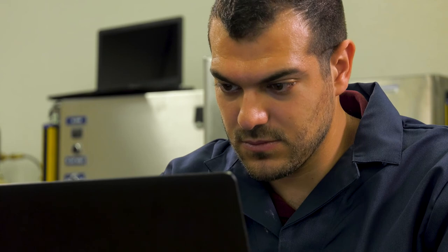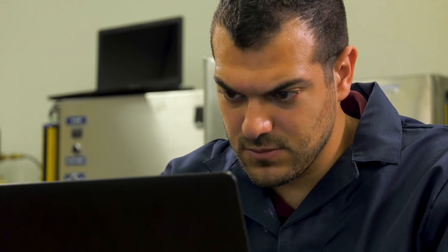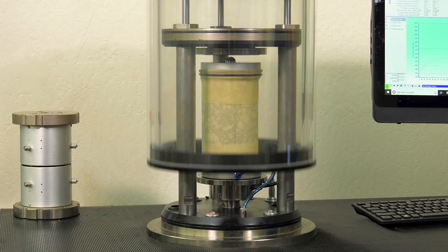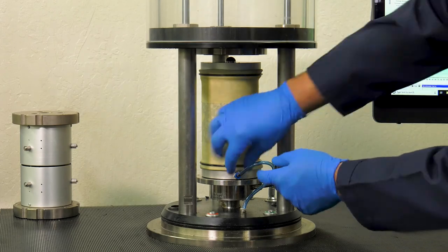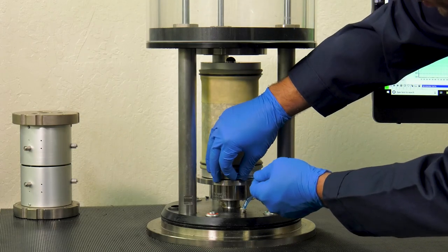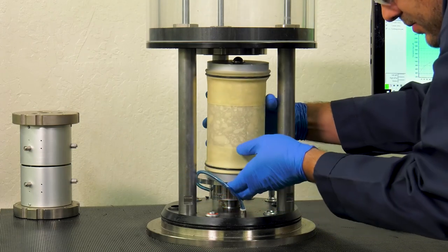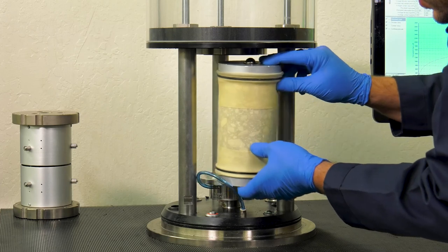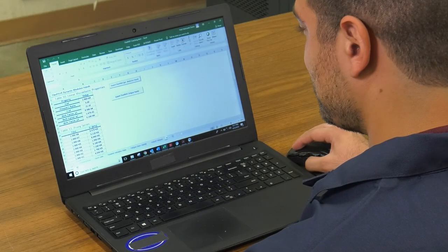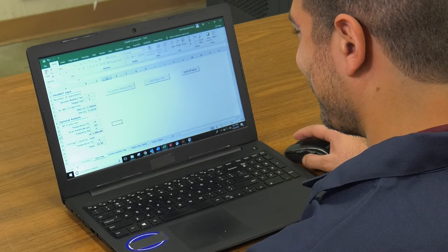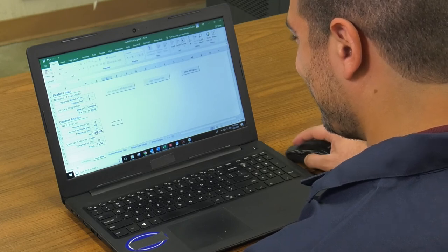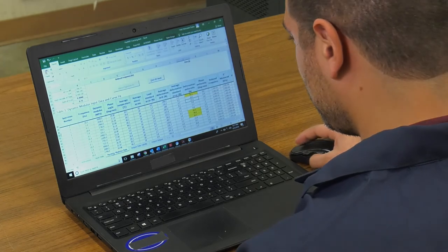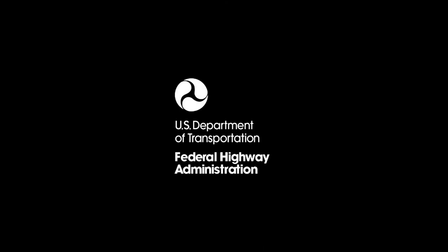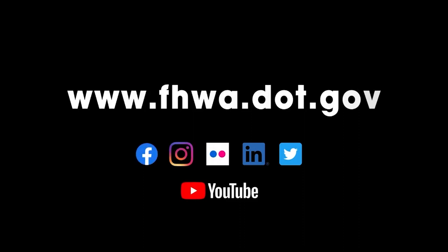When the test is complete, verify that all the data has been collected. Open the AMPT conditioning chamber, disconnect the drainage line, and remove the tested specimen assembly. Review your data. Check that it is acceptable and corresponds with AASHTO TP134 standards. For more information about Asphalt Mixture Performance Tester procedures or other pavement testing resources, contact the Federal Highway Administration.